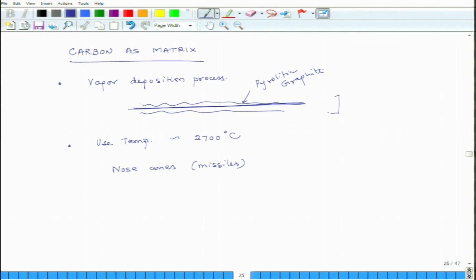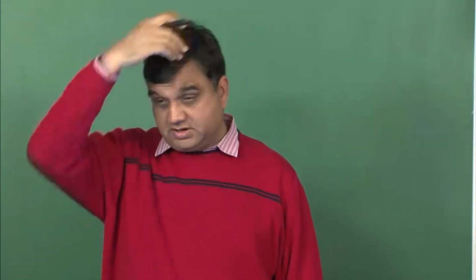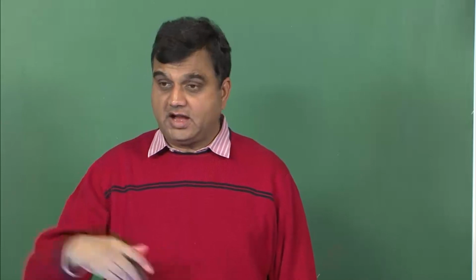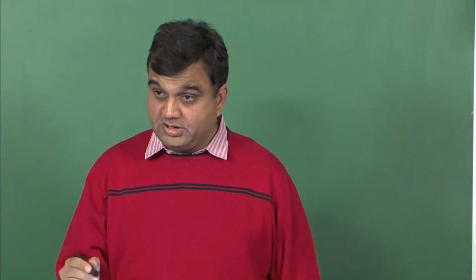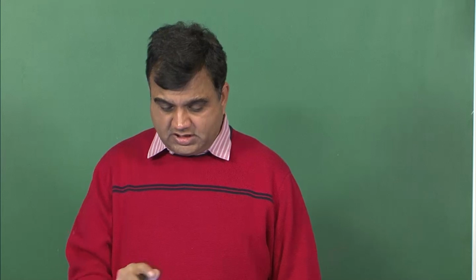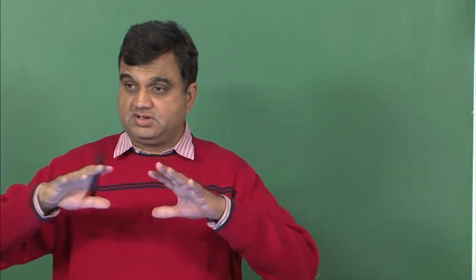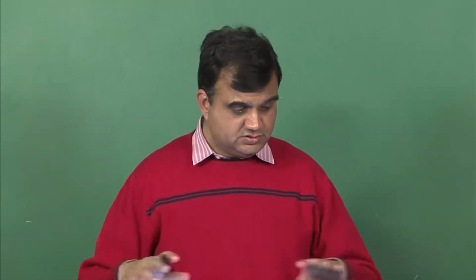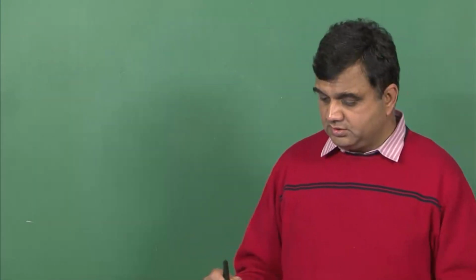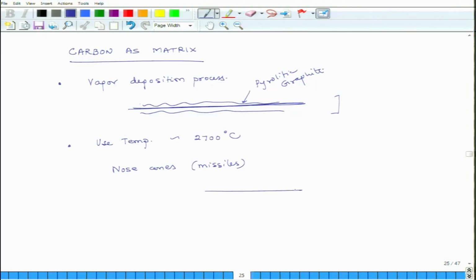But while using these, you have graphite as matrix and graphite as fiber, and it enters the atmosphere at 2700 or 2000 degrees plus temperature, it can right away burn. So, to make sure that it does not burn off and become carbon dioxide, you coat the entire thing with something which prevents oxidation. So, that is an important thing to consider. This is all we wanted to discuss in terms of carbon as matrix material.